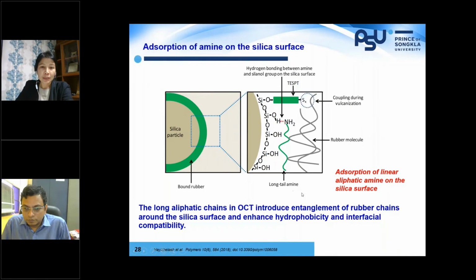What happened when we have this amine? When we have silica particles, we have bound rubber, a layer, and on the silica surface we have silanol groups. And as I mentioned, when we have this amine, it can interact with free silanol groups, so it changes the hydrophobicity, and also this long aliphatic tail of the amine can entangle with rubber molecules, and that helps to achieve properties close to what we actually wanted.